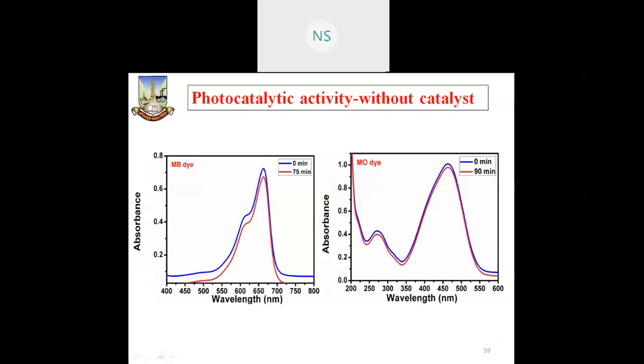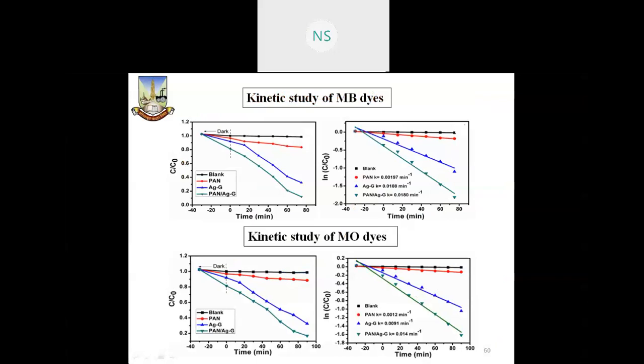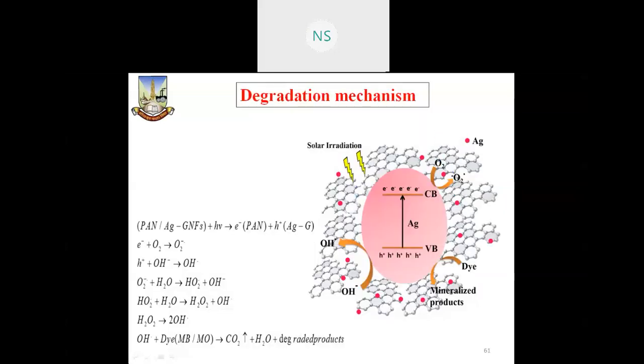Next. We have done the kinetic study for methylene blue and methyl orange. A first order, unimolecular reaction has been observed. Next. This is the degradation mechanism. Here is the silver, and because of the presence of the silver, the conduction band is changing. Then formation of electron and hole pairs takes place, and these oxidation and reducing products lead to complete mineralization. Formation of carbon dioxide takes place with removal of the complete dye from the surface of the water. Next.